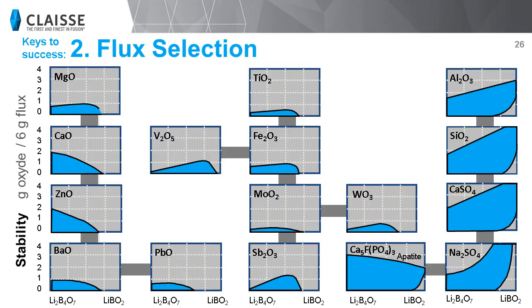Like any analytical chemistry method, you need to select the best dissolvent for your analytes in order to have the highest possible concentration of sample in your solution. The lithium borate flux acidity index may help you select the best flux for your borate fusion method. You can see on this graph a few common elements being analyzed. Each element has its own dissolution ratio based on the flux type. An element with a low oxygen content, such as calcium oxide, magnesium oxide, where there's one oxygen per element, will get a higher and better dissolution in a flux mainly composed of lithium tetraborate. On the other hand, an element with a higher ratio of oxygen, such as silicon dioxide, aluminum oxide, where there's more oxygen than the element, will get a better dissolution in a flux mainly composed of lithium metaborate.